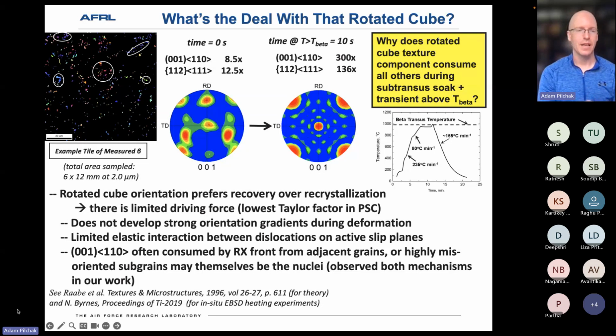And some of the reasons that were outlined for this were, with respect to the plane strain compression strain path, there's very limited driving force for recrystallization. That's a highly stable orientation that doesn't require a lot of dislocation activity or work put in to remain stable, and so it tends to prefer recovery over recrystallization. The other thing is that this highly symmetric orientation with respect to plane strain or rolling makes it so it doesn't develop strong orientation gradients. So measurements of rotated cube-oriented grains in single-phase materials show essentially no internal misorientation, whereas everything else around it has all these little subgrains forming.